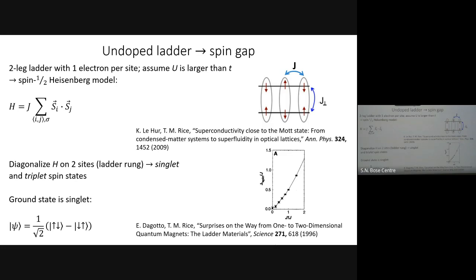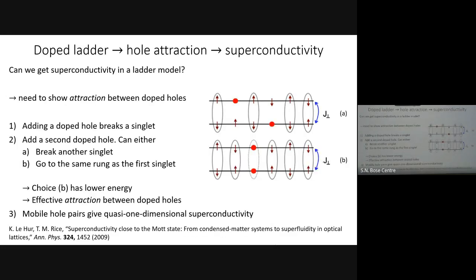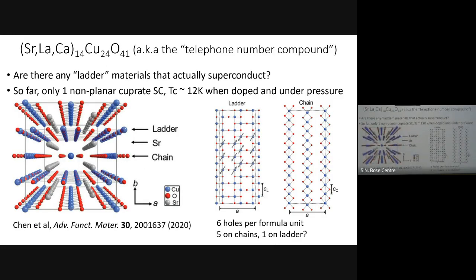These are paired. So what does that have to do with superconductivity? It's very easy: if I create a doped hole, if they're far from each other, I've destroyed two singlets. But if I've destroyed it here, I've destroyed only one singlet. So it is preferable to destroy them here. And then, of course, these singlets will move. This one moves here. Somebody talked about triplons. This is somewhat similar to triplons, except the system is not half filled and it's a conductor. So the conductivity is due to spin singlets, and you should get superconductivity. Is that true? Okay. Let me jump down.